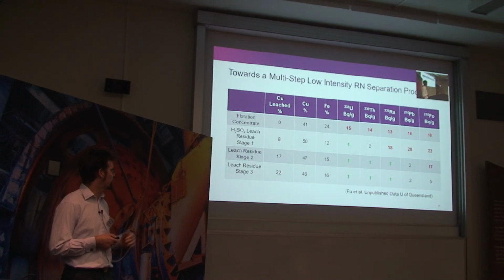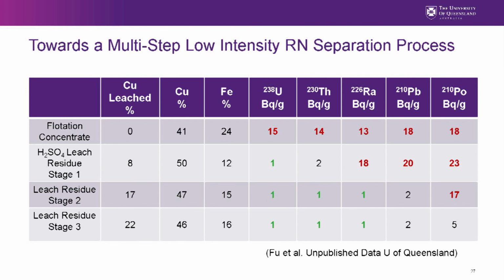Okay, so because of the challenges with high temperature metathesis, and the desire to separate at lower temperature, get these away from the copper concentrates, we're working towards a multi-step but low-intensity separation to remove the radionuclides. So I showed you already this sulfuric acid leach step where we can knock the uranium and thorium down. And we have second and third stages. In the second stage, we can knock the radium and lead down, a little bit of the polonium, and we have a third step where we're trying to target polonium, and we can get that down a fair way.